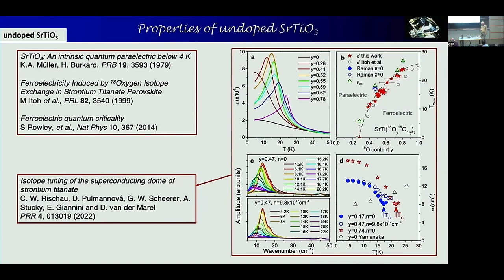Then at some point, the group in Cambridge, Rowley et al., realized that, okay, this is interesting because it means you have a quantum critical point as a function of the oxygen 18 substitution. At around 30% substitution, you go through a transition from paraelectric to ferroelectric, and so this is a quantum critical point, and maybe this quantum critical point may also be used to make the system superconducting. I'll tell a lot more about that, also about the superconducting phase later in the talk.